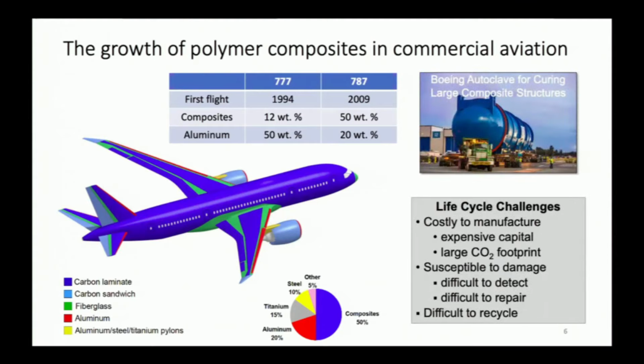You see it, for example, in wind turbines that are now sprouting up throughout the U.S. And if you just look at some of the life cycle challenges of this particular sector, the autoclave for the Boeing's Dreamliner, a very small section of the fuselage is up on the top. You can see that it's obviously going to be costly to manufacture. That autoclave is heated to 180 degrees for some 6 to 8 hours. So even just that single processing step has a very large CO2 footprint, and it's quite energy intensive. The ultimate cost savings energy-wise comes from the 30-year lifetime of the aircraft, as it's much lighter now to move that aircraft across the country or overseas.